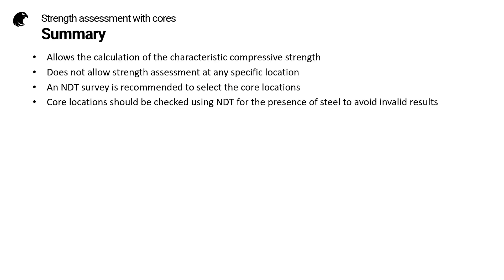To summarize strength assessment with cores: it allows the calculation of the characteristic compressive strength, but it does not allow strength assessment at any specific location. An NDT survey is recommended to select the core locations, and core locations should be checked using NDT for the presence of steel to avoid invalid results.